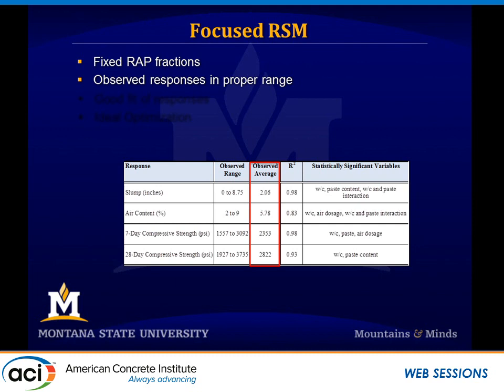So we ran this response surface methodology. Again, good fits. You can see that our observed range is about where our targets were at 1.5-inch slumps, 6% air, 3,000 PSI at 28 days. So we were in the general vicinity, so this one was going to work better. And our R-squared values, our measure of how good our equations matched the data, of 98, 83, 98, 93, so these are all good. So it was ideal for optimization.